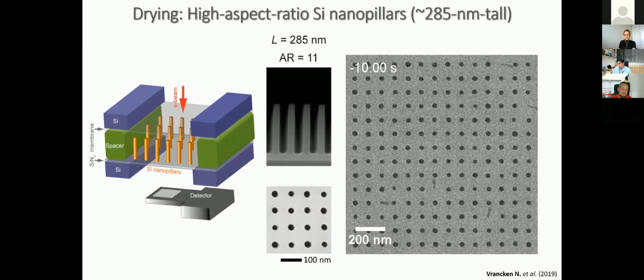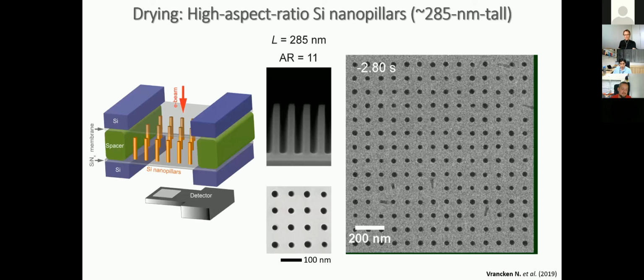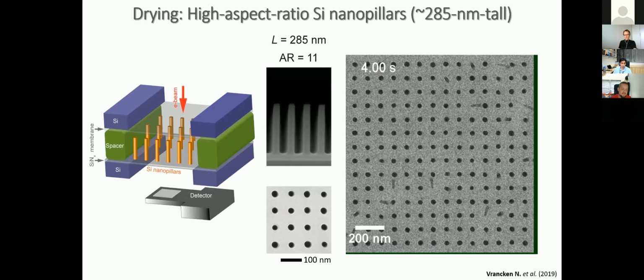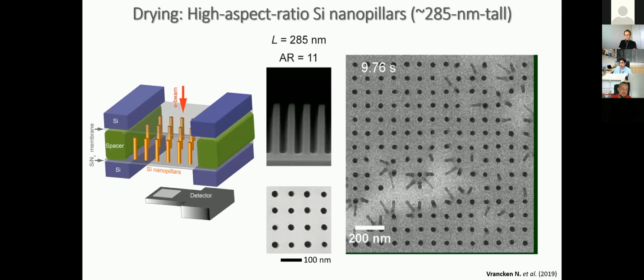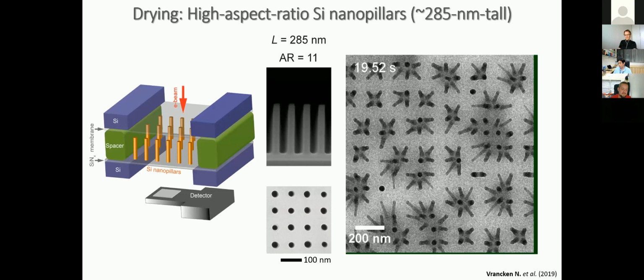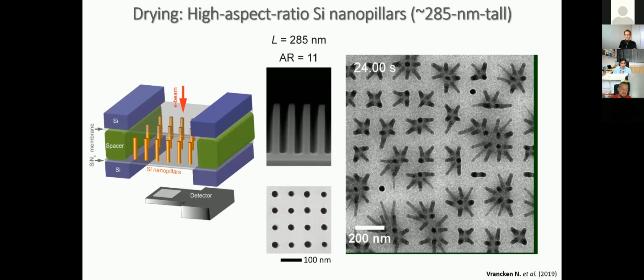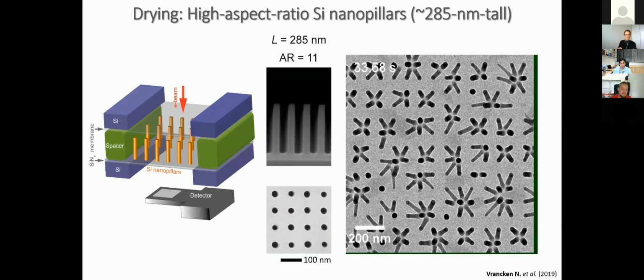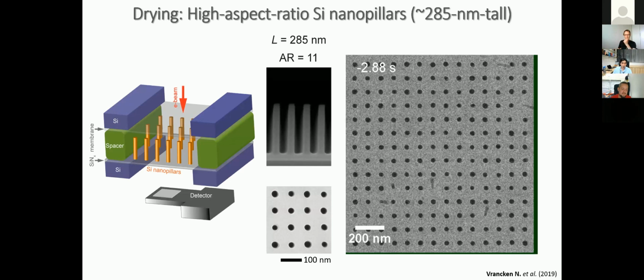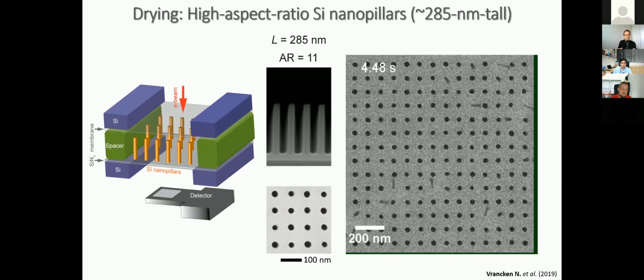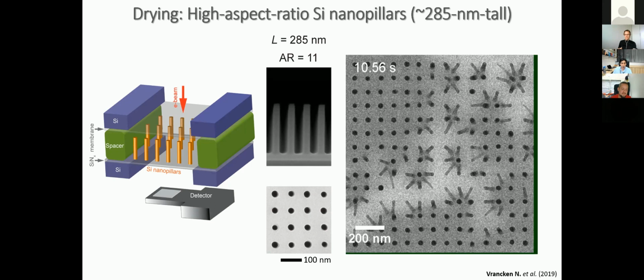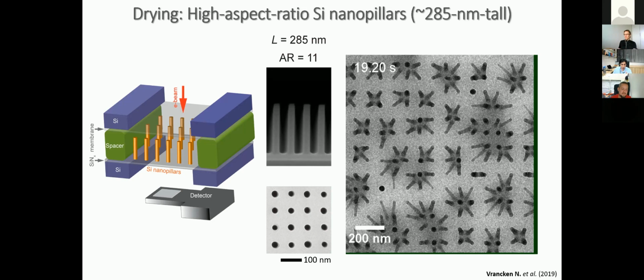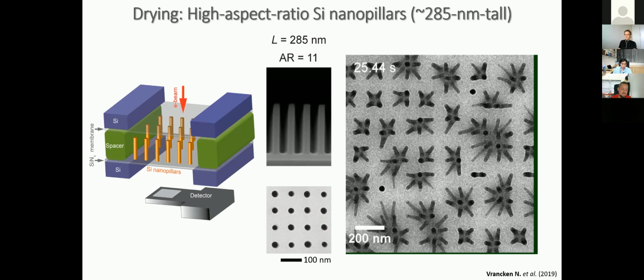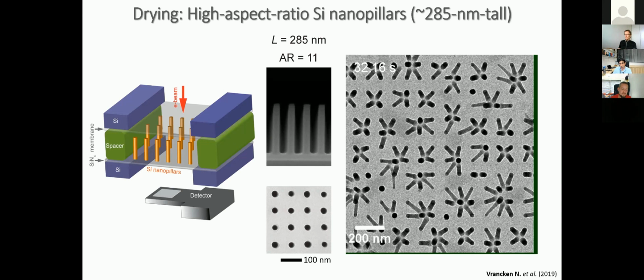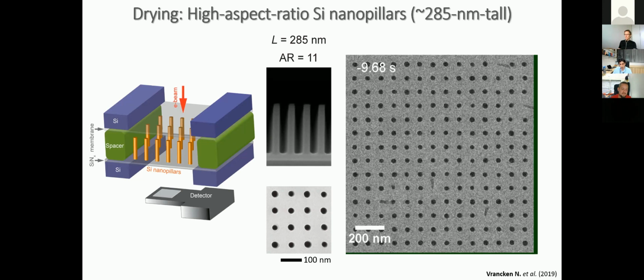And can we image these processes? And of course, this is what you're imaging here. What we're seeing here is a drying process, how nanopillars collapse during the drying, right? So as the liquid recedes, a small amount of water gets trapped between the pillars. So you form pseudo droplets, and these pseudo droplets have a capillary force that clusters them together and holds them together. And once all the liquid is evaporated, your structures are stuck. So this is a typical capillary damage.